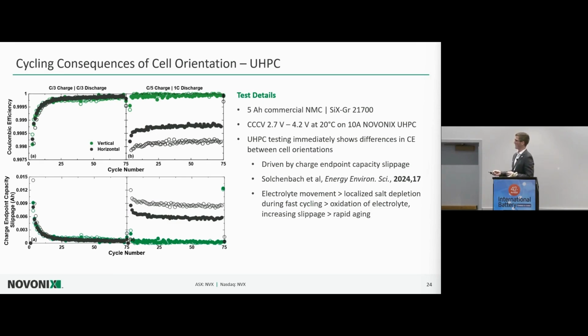And I say significantly different. This plot is really far zoomed in, as you can tell. But for UHPC, this is pretty significant. And this is all driven by charge endpoint capacity slippage. So we're driving some kind of slippage-based mechanisms here, oxidation or something.